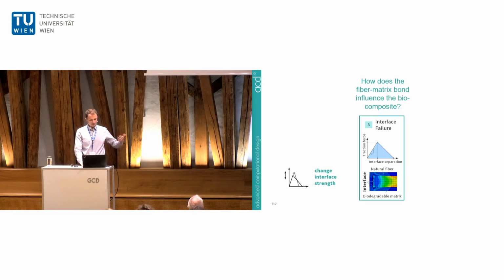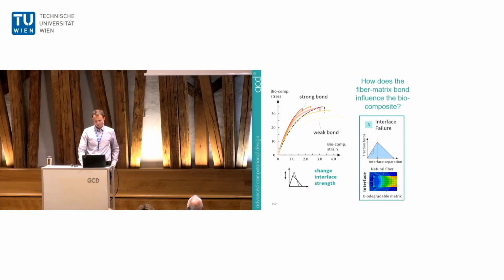So what happens if the interface is stronger or weaker? The upper curves here are results from the biocomposite simulations with high interface strength between fiber and matrix, and down below with low interface strength. And what happens if I shift here the slope of this traction separation law, basically meaning that we have a rather brittle or very ductile interface.